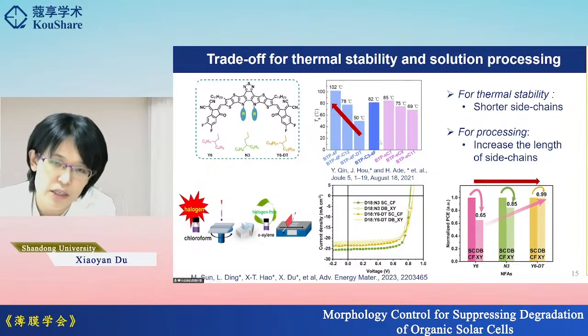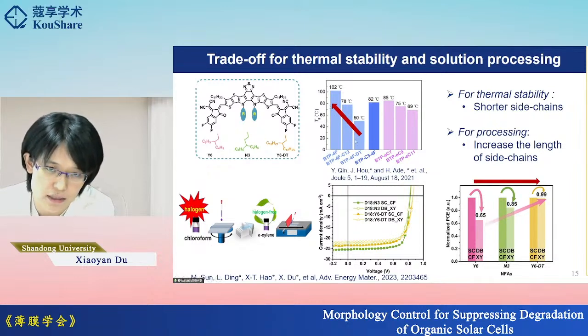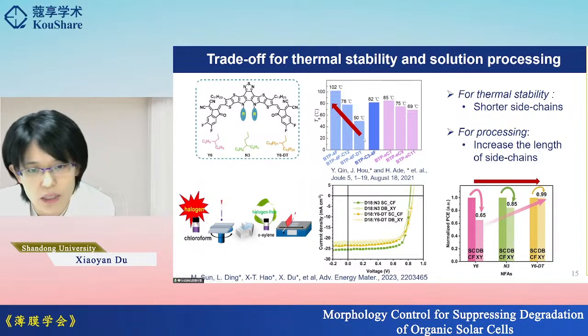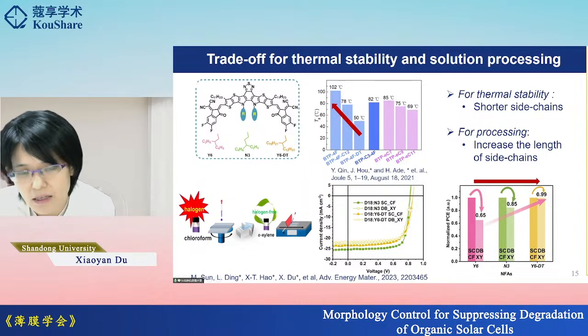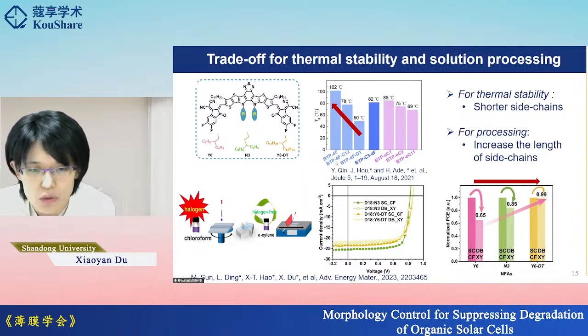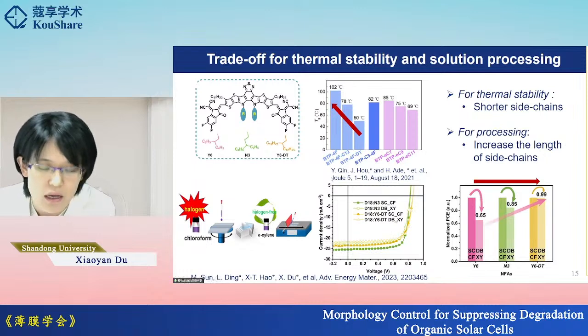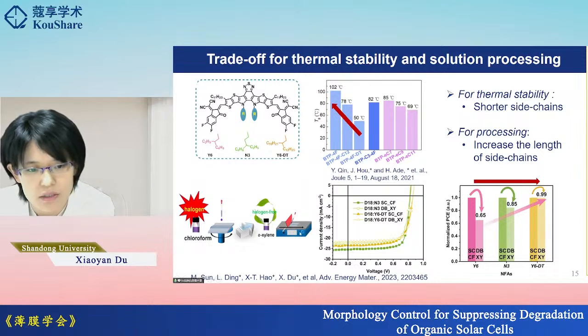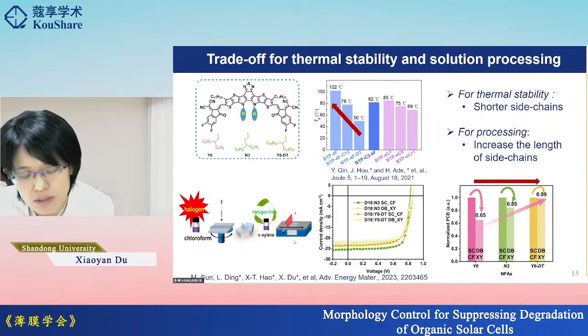In this figure, we show that if we make the side chain length shorter, the Tg will increase. But this guideline contradicts what is required for device processing with scalable methods. For example, in this work, we show that if we transfer the fabrication from spin coating with toxic solvent to more scalable coating techniques, including doctor blading and more environmentally friendly solvents,